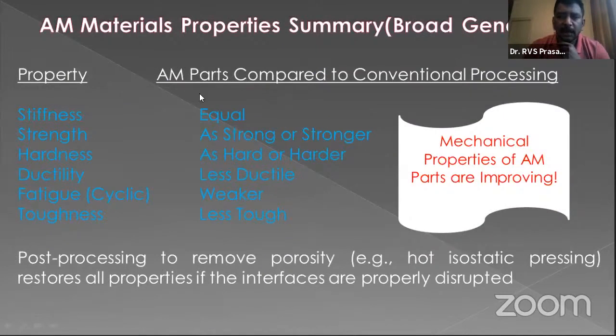So in broad generalities, look at properties like stiffness, strength, hardness, ductility, fatigue, and toughness. These are very important aspects of any component. When you compare with conventional processing, stiffness is more or less equal in the case of AM parts, strength is as strong as or stronger, and hardness is also as hard or better. But here the challenge is ductility. AM parts are much less ductile compared to conventionally manufactured parts.